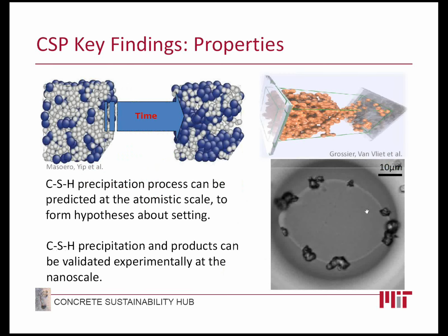onto the properties. We're concerned with various levels of properties, and Professor Palant gave you a nice overview of that. One of the areas that we're interested in is understanding how to predict the precipitation of that CSH, or calcium silicate hydrate phase, because that's one of the most difficult aspects of cement paste formation and the resulting concrete product to predict. So we're actually developing new ways to understand and predict precipitation at the atomistic scale, and then we're going to form hypotheses. We've actually begun to form quite a few hypotheses in terms of how is this affected by the calcium to silicon ratio, how is this affected by pH, by temperature, by choice of clinker.